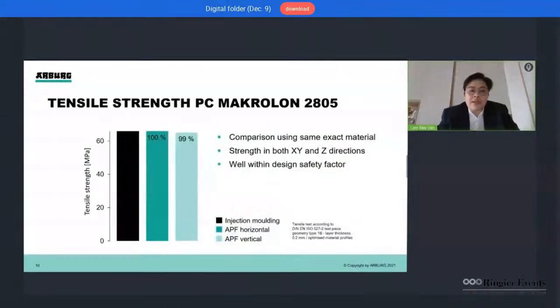The mechanical properties that can be reached are very comparable to injection molded parts. We did a study printing some tensile bars to show how close the mechanical properties really are. The black bar here shows the properties based on polycarbonate. The dark green shows strength printed in the flat, horizontal direction, which is XY, and the light green shows the tensile bar printed upwards, in the Z direction. Generally, the Z direction is always weaker due to the 3D printing process, where the layers are stacking on top of each other.